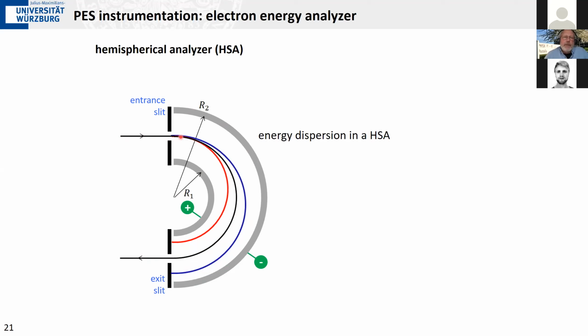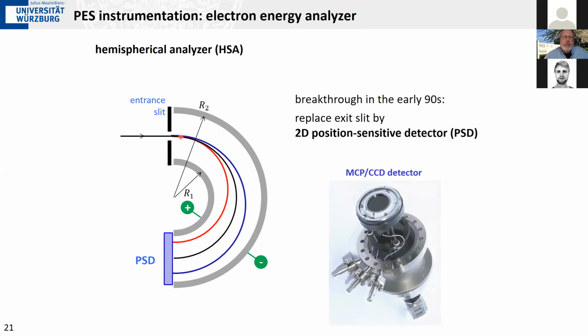This was the way such analyzers have been used up to about the mid-90s or so. And then the community has made a big step forward by utilizing the progress in detector technology that comes mostly from the people working in the field of X-ray diffraction. They had developed different types of two-dimensional, position-sensitive detectors. And that allowed us to replace the exit slit by this 2D detector, because now we do not just measure the energy of the electrons hitting the exit slit, we can measure all photoelectrons with different energies simultaneously, and that of course gives rise to a much faster measurement.